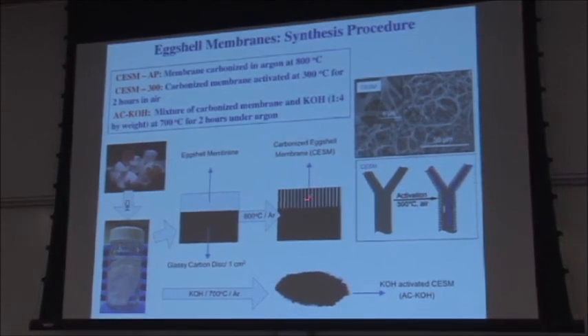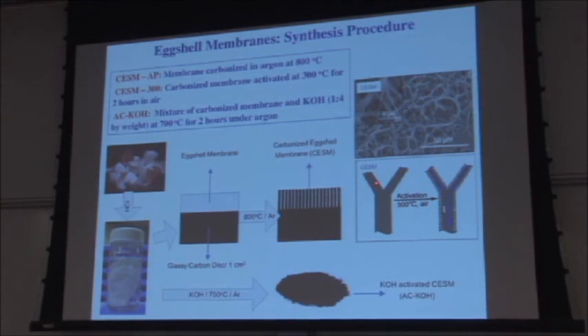And what we did is we got this, it's a very mild activation as far as, if you ever played around with carbons, 300 degrees C in air is considered very mild. And it's a short duration. So what we got is still a low surface area material, but on the outside, we're able to achieve enough mesoporosity.